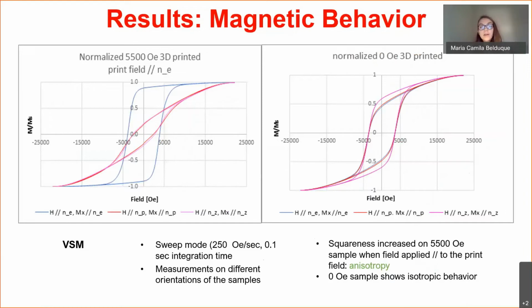Here, the second curve shows the magnetic hysteresis for the zero Oersted printed samples for different directions of the applied magnetic field with respect to the sample's axis. Since the samples were printed with no magnetic field, the hysteresis curves show a much more isotropic behavior, with curves that are similar in all directions.